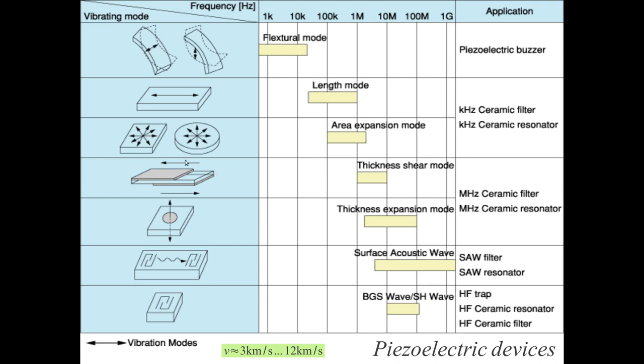Because shear waves do not propagate in gases. So if we want a high Q resonator, we don't want the mechanical energy propagating in the surroundings. So if you have just a length mode or a flexure mode quartz crystal, then we need to install this crystal in a vacuum envelope. While thickness shear mode devices can operate in air at ambient pressure because shear waves cannot propagate in air. We have another mode, thickness expansion mode. We use thickness expansion mode in film bulk acoustic wave filters. We will see that later on today.